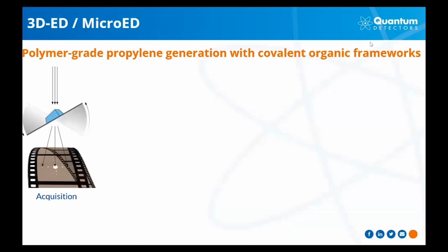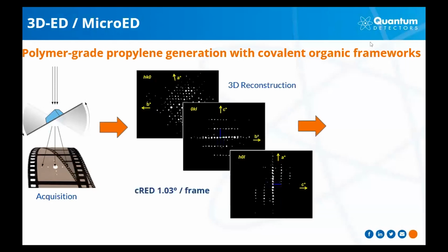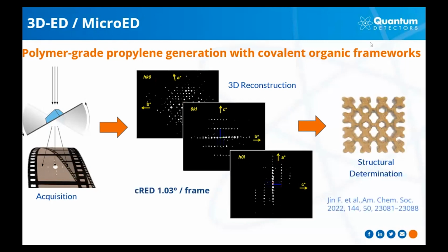As a last example, I would like to show you microelectron diffraction acquisition. Basically, we can continuously rotate the sample or do it in steps. In this case, data has been collected from a propane and propylene sample, where the two compounds were suspended in a covalent organic framework 3D structure. Once we collect this 3D data set, we can reconstruct the information in the diffraction space, and from there match the structure of the sample with different libraries.